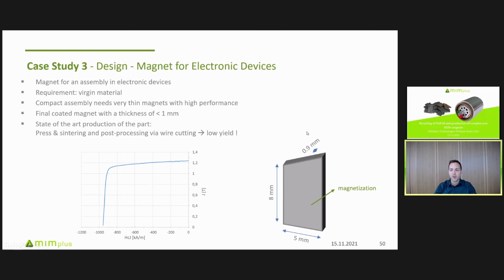of below 1 millimeter. That is quite critical if you look at the conventional production processes, because there you produce larger blocks and then cut them via wire cutting, and then these thin magnets are quite fragile, and you have a lot of scrap that you get during wire cutting. So the yield was quite low. With our MIM process, we realized to produce the parts in one shot without any post-processing.